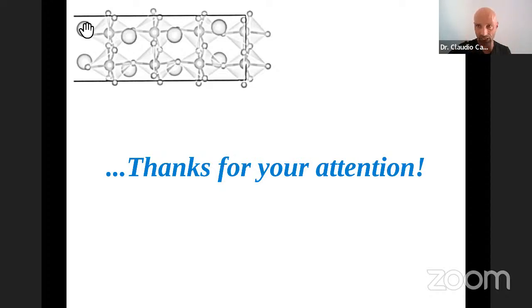However, that's not the case, of course, because we have some dipoles, surface dipoles, for instance, that will also change as you have some strain applied to the materials because they are piezoelectric. You will have changes in the band gap, for instance, that we haven't considered. But that's why we have done our validation for zinc oxide and for silicon carbide at the end. The final slides are shown, right? In there is no assumption. There is just the DFT calculations, right? So in that case, you have all effects.